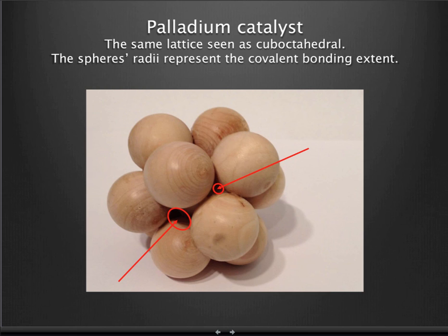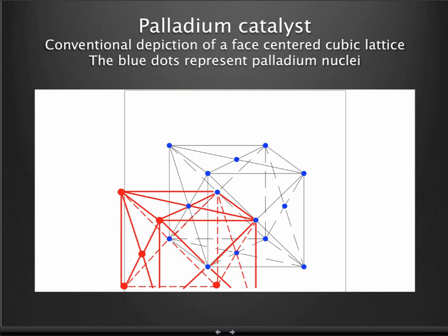In the interior of the lattice, around each sphere, there are 12 identical spheres. While it is perhaps not apparent in the last slide of the face-centered cube, each face-centered node constitutes a vertex node for another interlocking set of unit cells, one of which is shown here, so that every sphere not on the exterior layer of the lattice is similarly surrounded by 12 spheres.